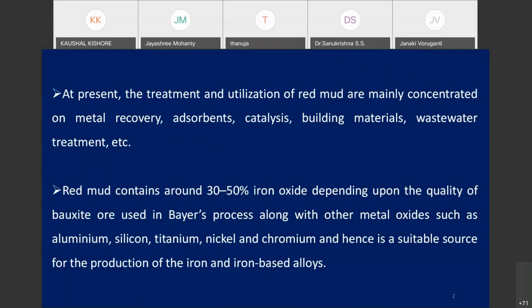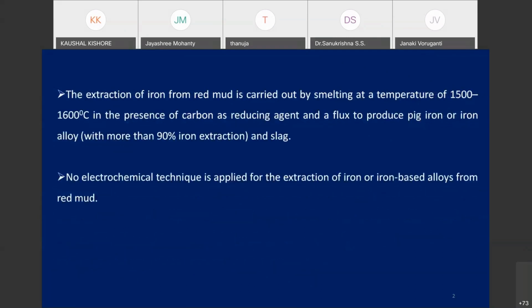Now, depending upon the sources of the red mud, the characteristics of the metals present in the red mud are different. So depending upon the source of bauxite material you are using, the metals differ. But mostly it contains aluminium, silicon, titanium, nickel, and chromium, and hence it can be a suitable source for production of iron or iron-based alloys. And if you see the literature available till now, people are extracting iron or iron-based alloys from the red mud through smelting at a very high temperature of 1500 to 1600 degrees centigrade in the presence of carbon as the reducing agent.